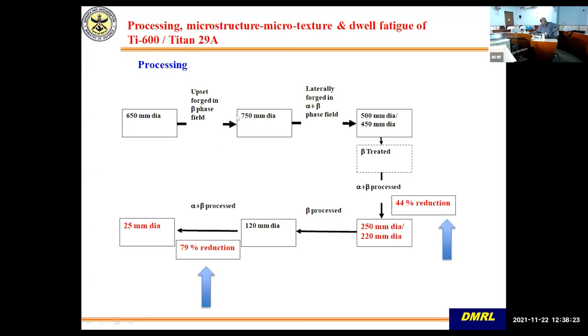Now, this is an example of how IMI 834 was indigenously produced with DMRL technology. It was triple melted, 650 mm dia. It was upset forged in the beta phase field to 750 mm dia, then laterally forged in the alpha plus beta field to get a 450 mm dia billet. Then it was again beta treated and again alpha plus beta processed and got 250 mm and 220 mm dia billets. This was used for making discs and rings. So what you see here is around 44% alpha plus beta reduction. Then this was further processed for making 25 mm dia rods for making blades, and it saw around 79% reduction in alpha plus beta processing.